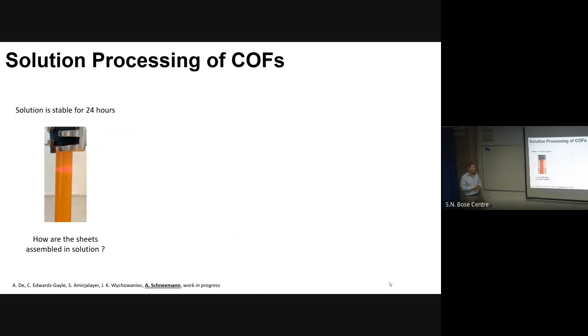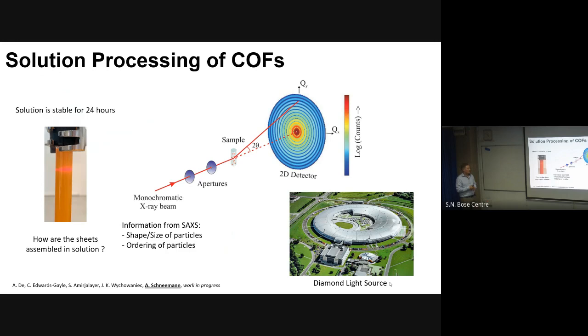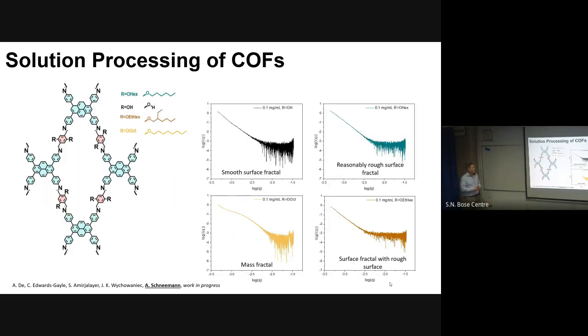Then I was pretty intrigued by the stability of the nanosheets in solution. So we see that for 24 hours they are stable, and I was interested in how these nanosheets are assembled in the solution, what is their state. So we did some synchrotron measurements for small angle X-ray scattering experiments at the Diamond Light Source, which is close to Oxford in the UK. From these you can learn something about the shape and the size of particles in solution and about their ordering.